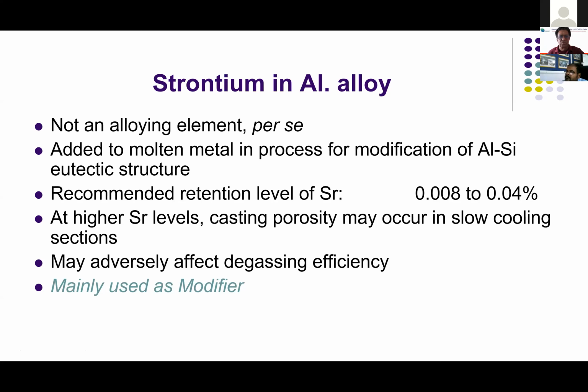Sodium is no longer used. Strontium also is added in the form of master alloy or small pellets and in the holding furnace. We can also tell the alloy maker to add this strontium and supply to you when he supplies the ingots. On remelting, if it is sodium modified, sodium is lost. Whereas strontium, we don't lose it actually, and the modification effect still remains. At a higher strontium level, casting porosity may occur in slow cooling or thick areas. So therefore, we don't recommend it.